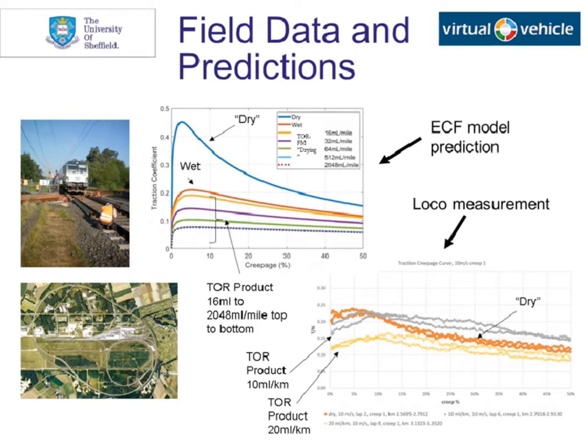So it's very likely that these were actually wet in reality. More importantly, though, if you compare the data for the top of rail product, you can see that there's really good correlation between the predictions and the actual measurements from the locomotive. So we're very clearly showing you can do some lab tests, tune a model that is then able to be used to give valid predictions of what will happen in the full-scale contact. It's really, really useful.